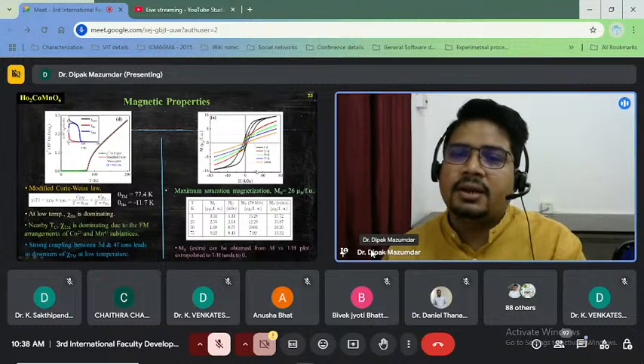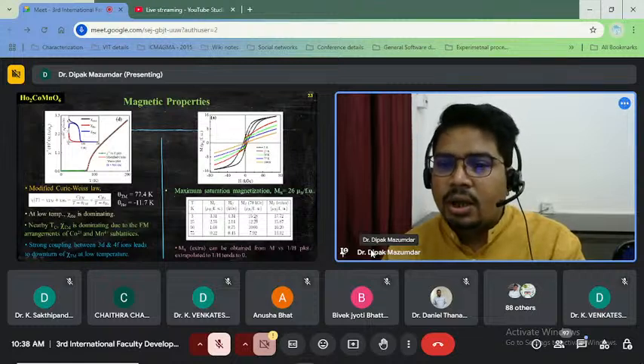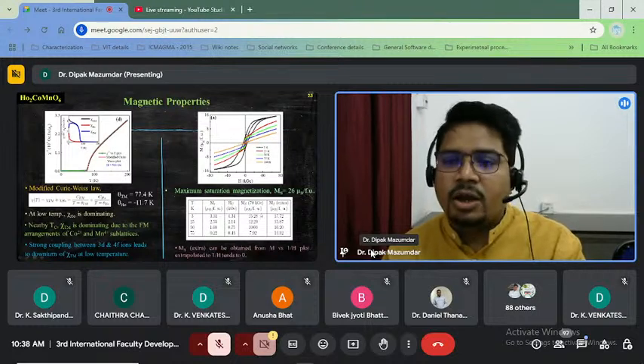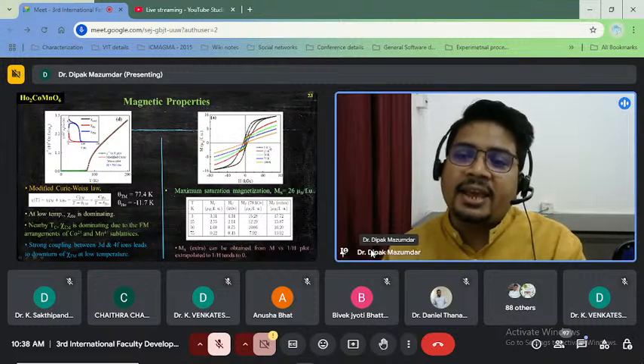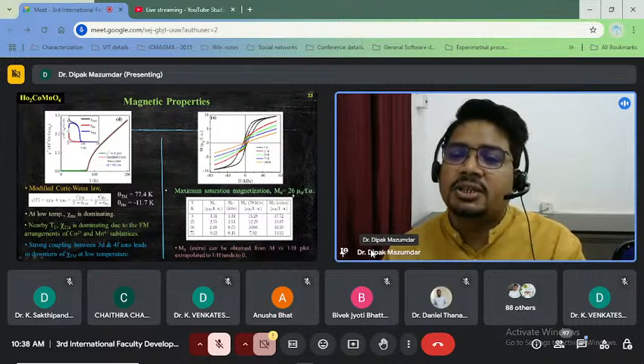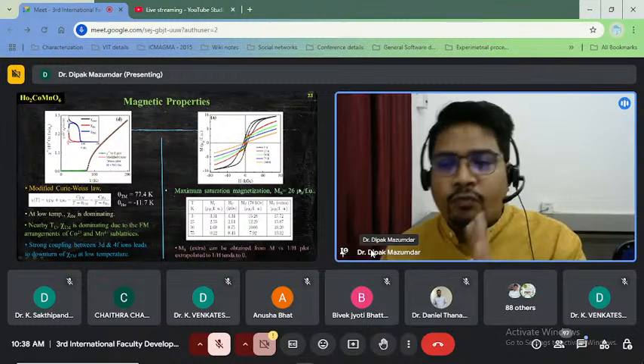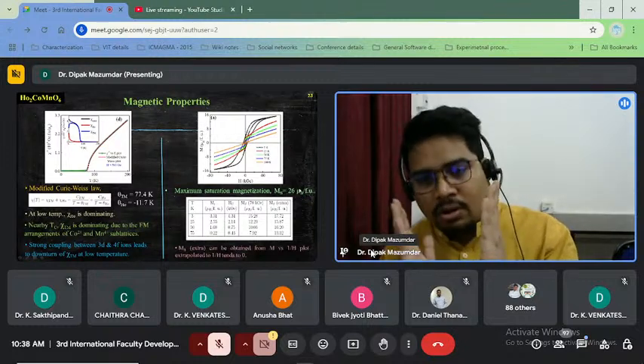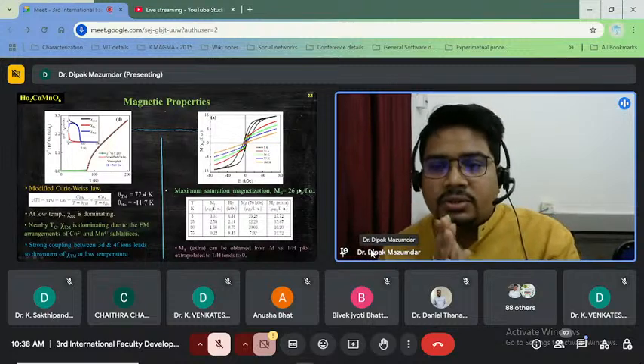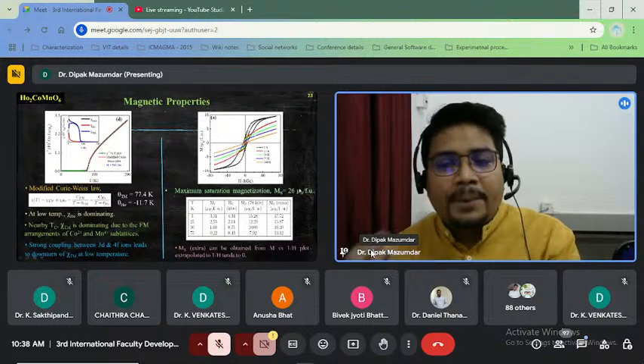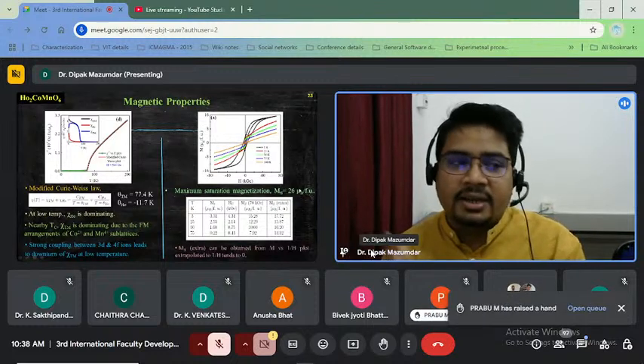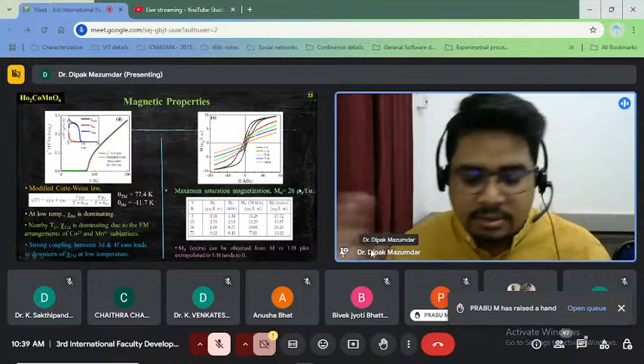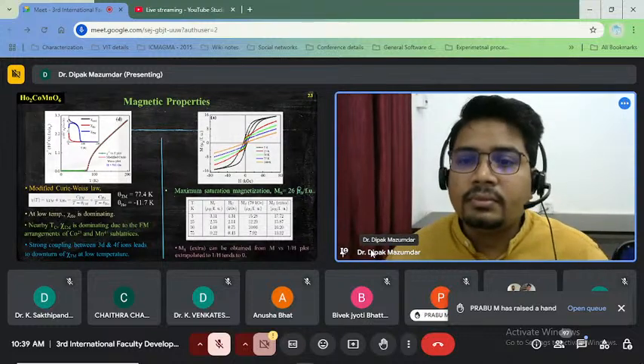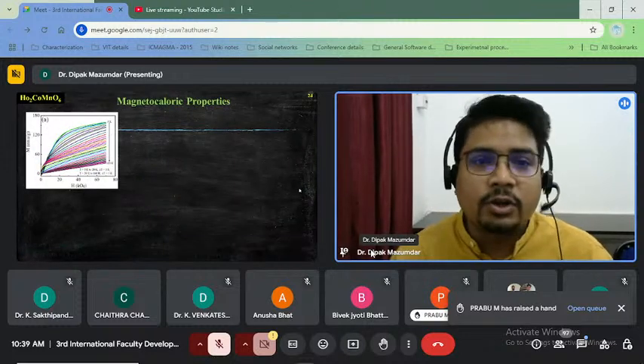And we have seen that the observed saturation magnetization for this compound is around 15.28 μB per formula unit at 70 kOe, but we expected that the saturation magnetization is around 26 μB for fully ferromagnetic alignment of all the three magnetic sublattices. So this reduction of saturation magnetization is possibly due to the presence of anti-site defects, which I will explain in later slides. Next, I am discussing the magnetocaloric properties.